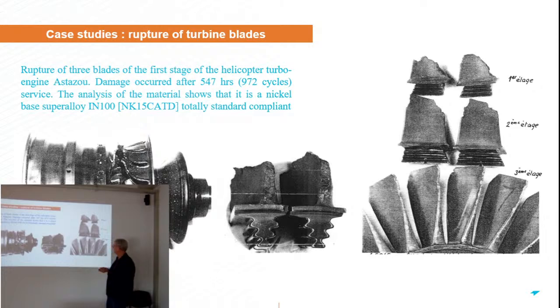Okay, and I show you the last example here, which is the fracture of turbine blades on the first stage of a helicopter turbo engine, again, and the damage occurred after 972 cycles, about 547 hours. The analysis of the material showed that the grade is Inconel 100, which is okay with us in terms of standard components. So you can see here the fracture of the first stage blades, and you can see also that after fracturing those blades, damage occurred on the second stage as well as the third stage. So all stages are damaged, but the root cause was the first stage blades fracture.